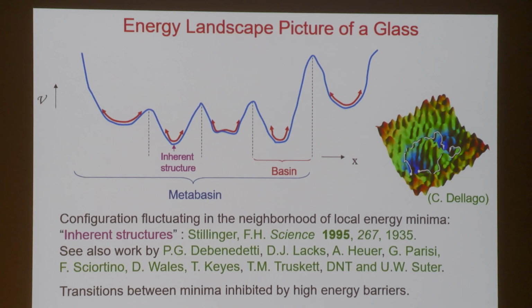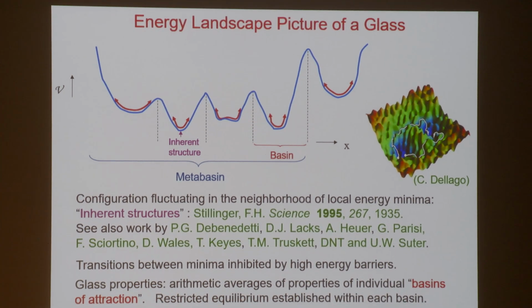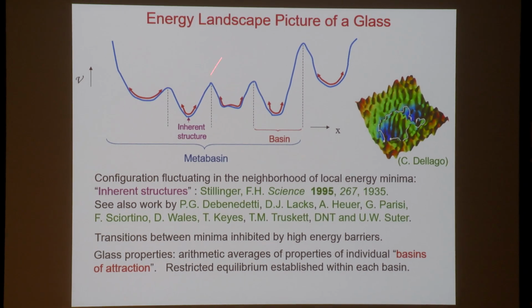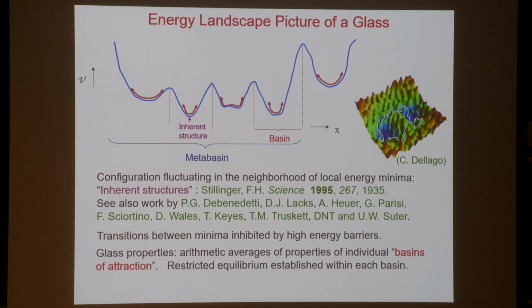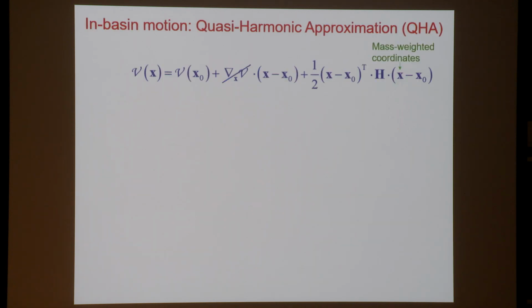So when we measure the properties of a glass, we essentially measure arithmetic averages of the individual properties of these basins. These are arithmetic or quenched averages as opposed to Boltzmann-weighted averages, because there is a restricted equilibrium established within each basin. So our first concern is to create such minima of the potential energy with respect to the microscopic degrees of freedom, and we do this by taking a well-equilibrated melt and quenching it down to low temperature to form a glass. While the melt is confined inside the local minimum, we will invoke a quasi-harmonic approximation.